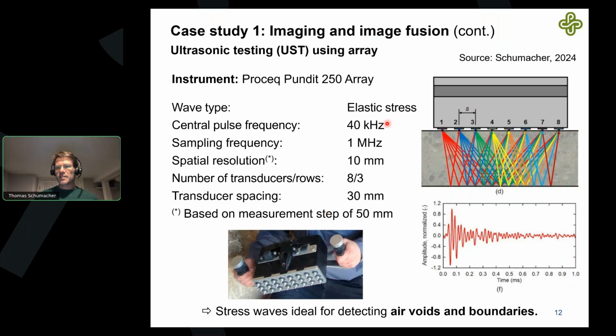This is about 40 kilohertz. This is now based on an elastic stress wave. It's in the ultrasonic range, like 40 kilohertz is ultrasonic, so not in the audible range. The spatial resolution, that's up to you. You can basically put this instrument down, take a measurement, move it to the next position, and the next position. For this project, we used a 50 millimeter step, which gives you a spatial resolution of about 10 millimeters. Stress waves or ultrasonic waves here are really ideal at detecting air voids, boundaries. So this is what you can use to get the thickness of a member, or in our case, we were hoping to see the voids inside, if there are any.